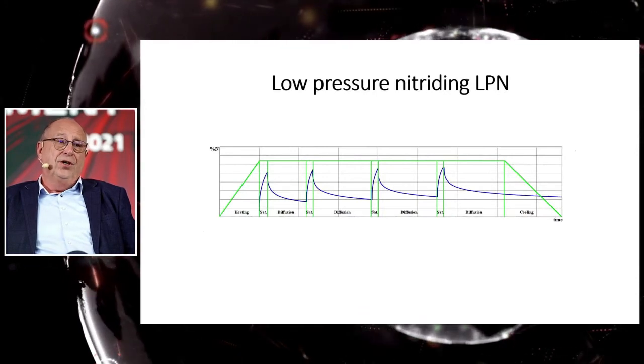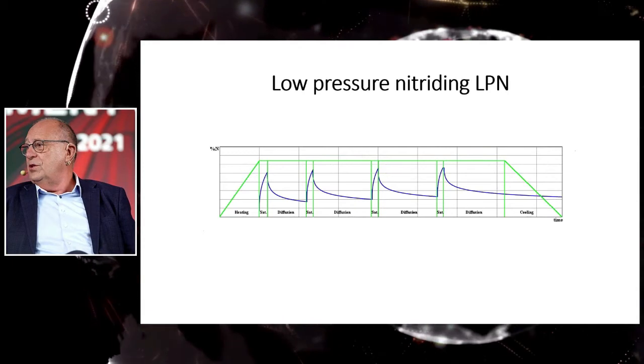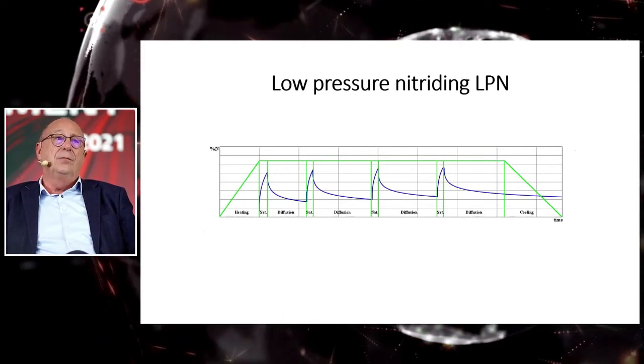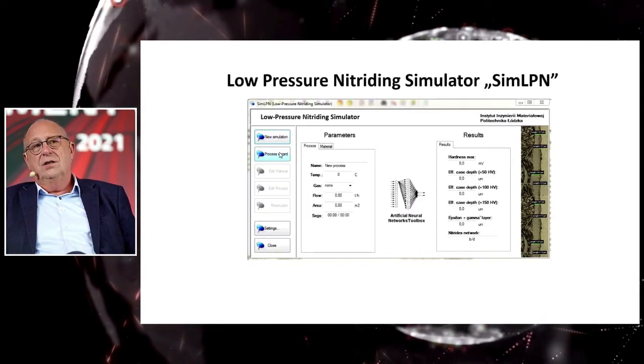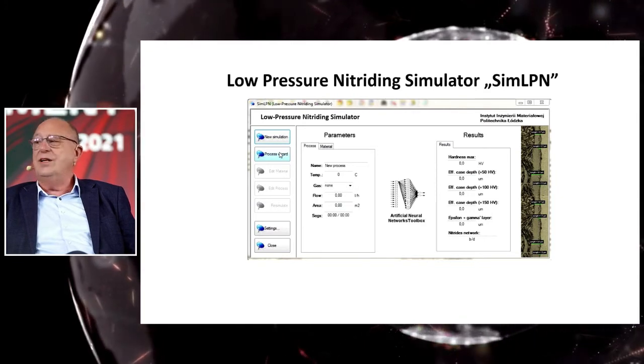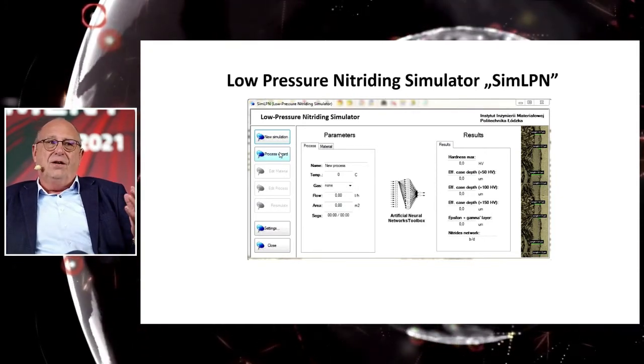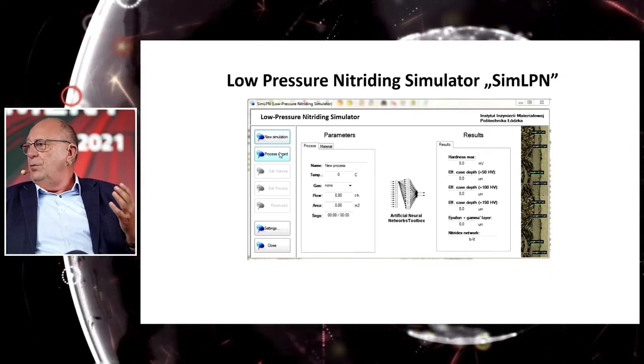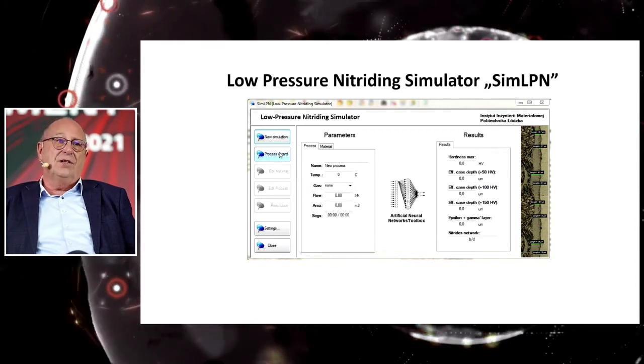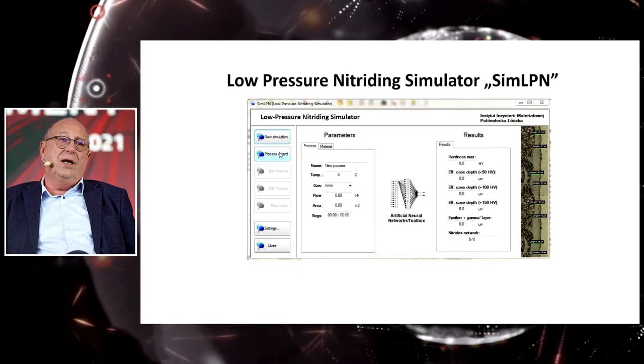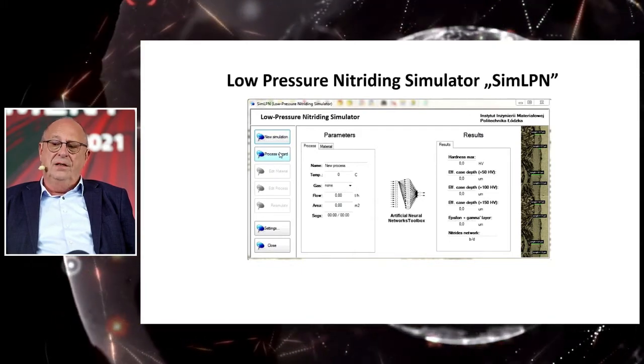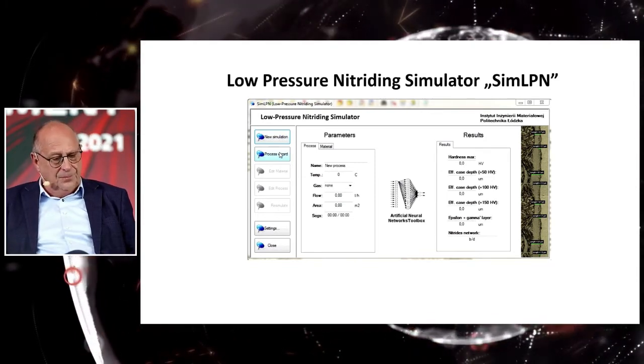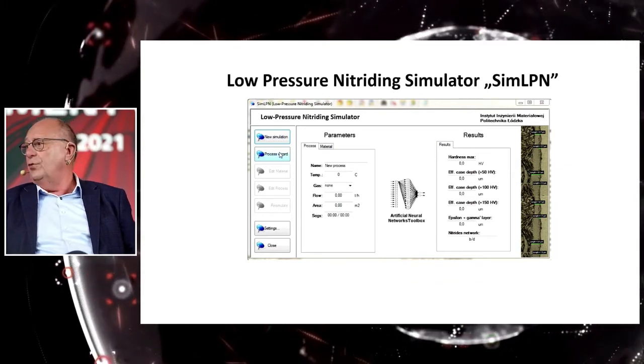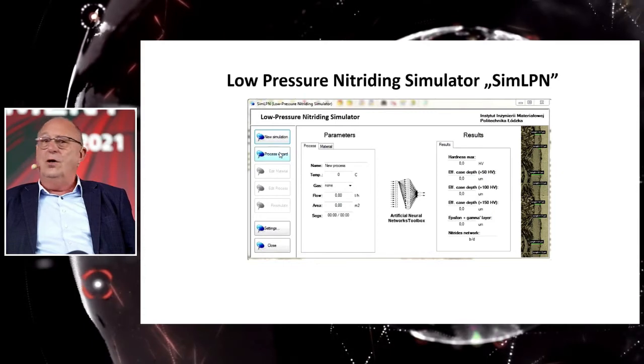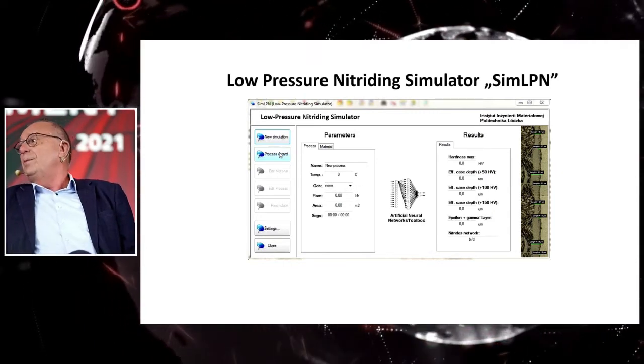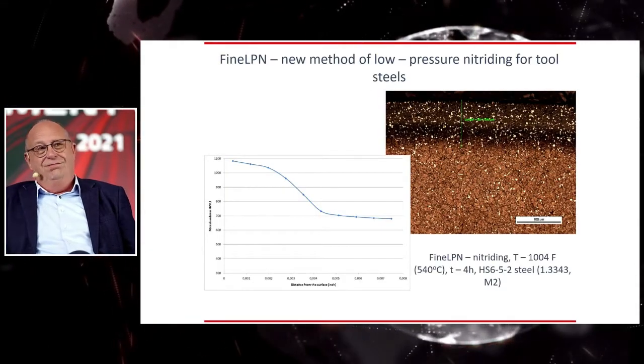So also here the process must be divided into the boost and diffusion state, rich in nitrogen and poor in nitrogen. But comparing to the carburizing, the problem is more difficult, because it is not one phase diffusion. There are several factors which influence the development of nitrogen profile and microstructure. Therefore, our proposal was to apply a neural network to solve this problem, and to teach this neural network on a very large experimental base.